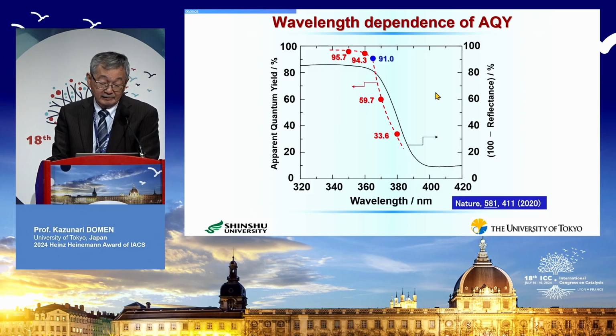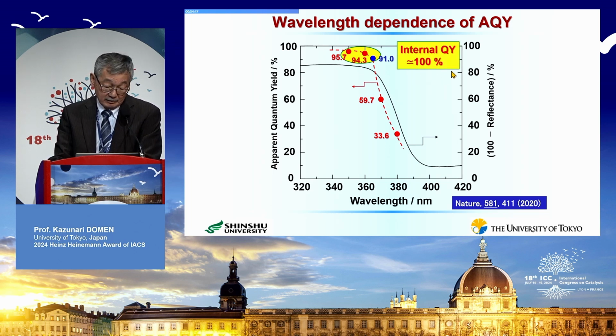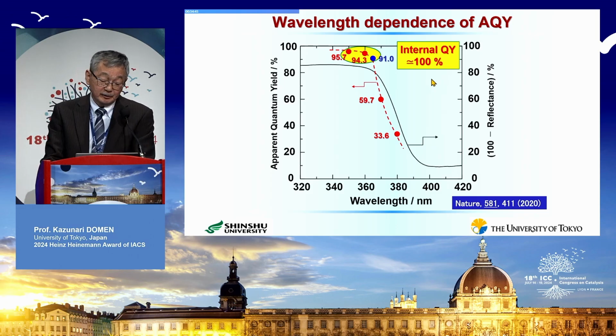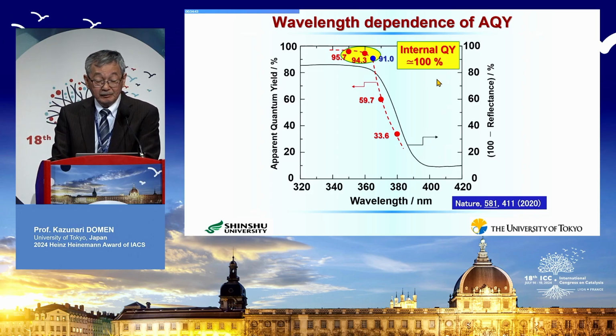So we consider that if we could measure the so-called internal quantum yield, I mean that's based on the total photon number which was really absorbed by our photocatalyst, at least in this region, we consider that internal quantum yield is already very close to 100%. So I would like to say that it is possible to split pure water into hydrogen and oxygen using a particulate photocatalyst with a quantum efficiency of almost unity.